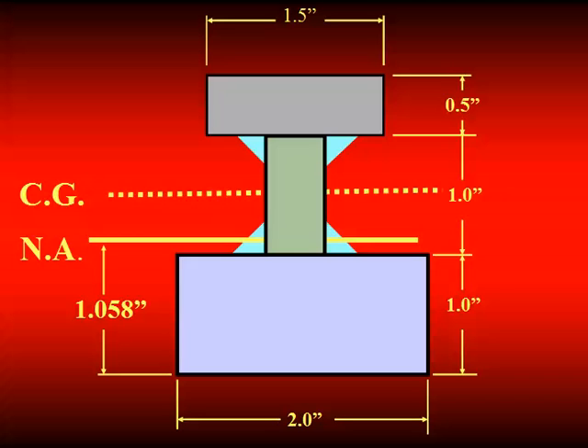Look at the top T all by itself. Does everyone see that the center of gravity of those welds and the neutral axis are concurrent? So if I go back a couple of principles, if I weld at the neutral axis, I should be able to weld this up distortion free, right? So I make one of those up, and indeed that comes out to be the case. Now this has done all the shrinkage it's going to do. I don't have to worry about that one anymore.